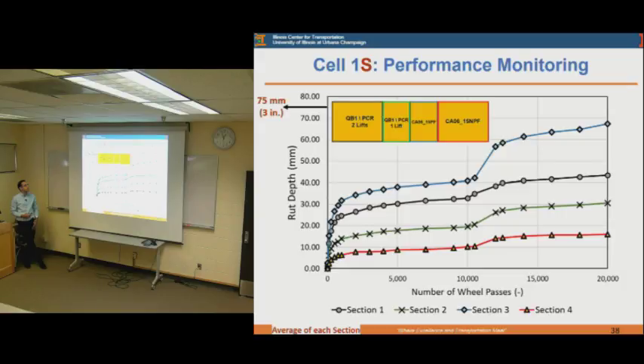So this is a summary of the rutting progression up to 20,000 passes of the construction platform test sections. And as you can see here, and as I said, the section that had the best performance was section 4 with the 15% non-plastic fines, followed by the section that had the quarry byproduct mixed with the primary crusher run in 1 pass, and then the sections that had the quarry byproduct constructed in 2 lifts, and the plastic fines test section. And this increase that you see in the test sections is after the incident of the heavy rain that I was showing.